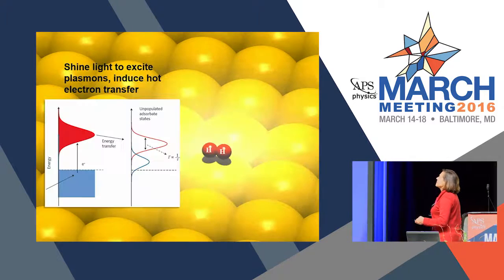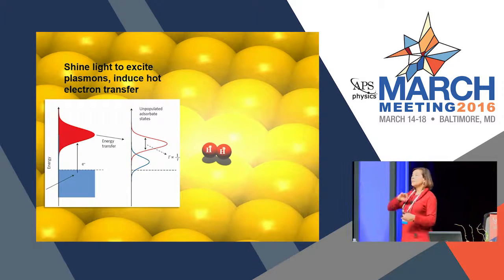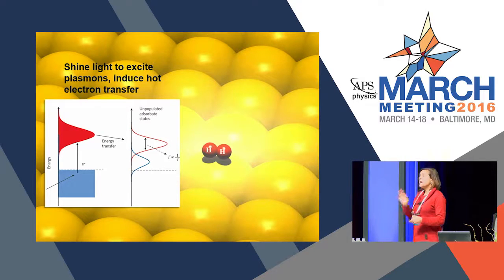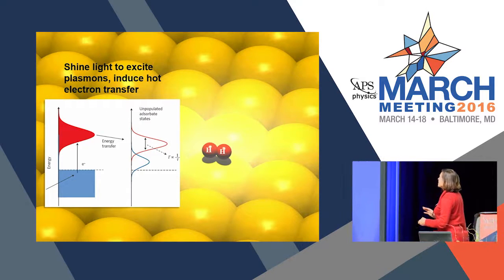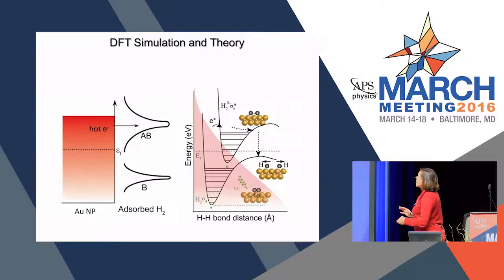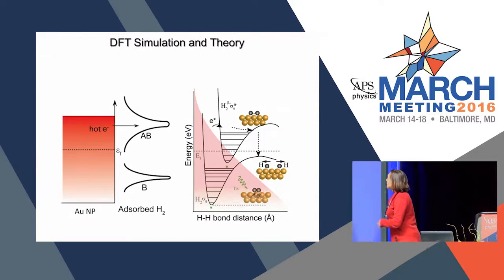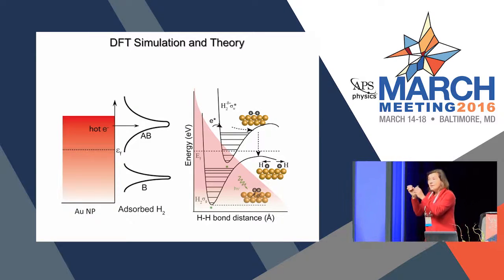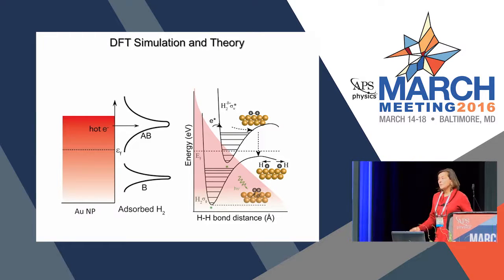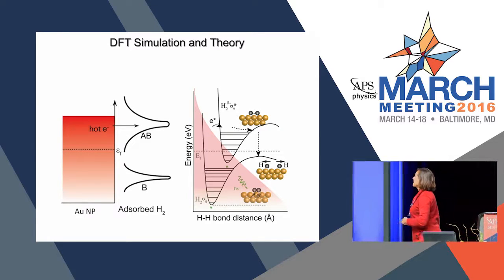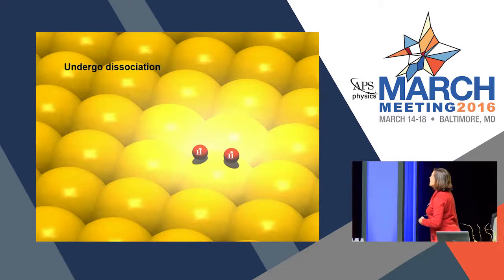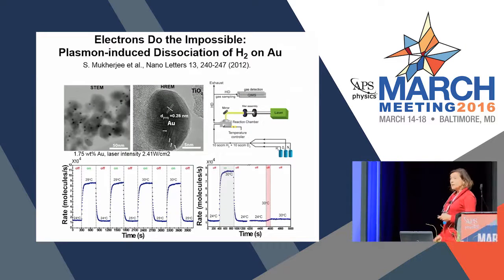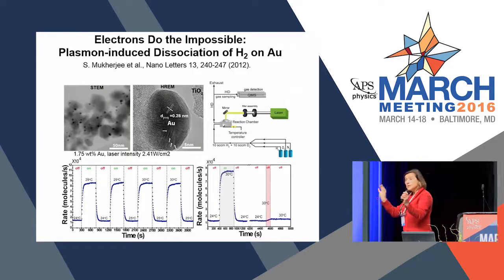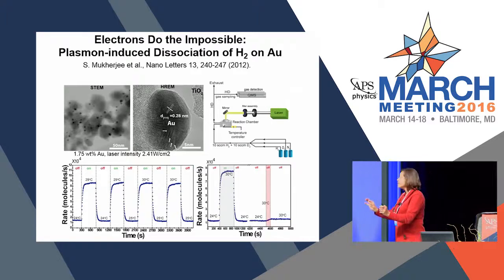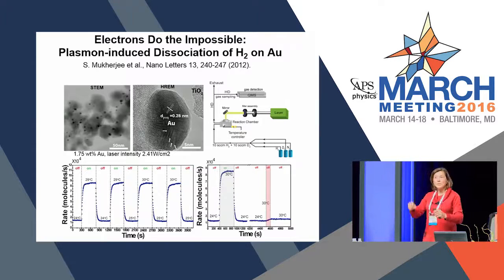They might weakly associate with the surface, but then we excite the plasmon in the metal. The plasmon decays to generate a hot electron, and that hot electron transfers to the LUMO level of the molecule, okay? And then the molecule dissociates. It falls down to this repulsive potential, and we see a dissociation of the molecule. And so we can basically do light-induced dissociation, right, all at room temperature very easily. How do we measure this?